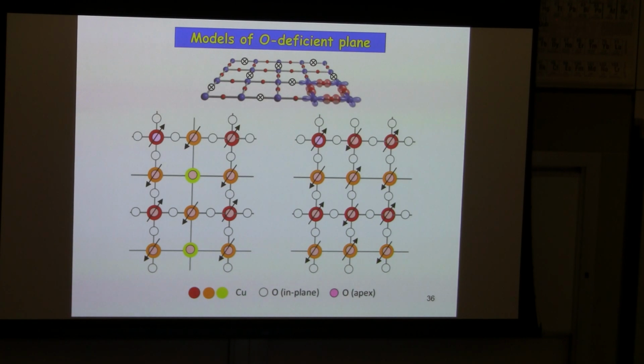Particularly important is that now we have an oxygen deficient copper oxygen plane. In many places, such a superexchange coupling is disrupted, then there is basically no contribution from this four cyclic spin term that is negative to the actual superexchange coupling constant. So we expect that in this oxygen deficient oxygen plane, we expect larger magnetic coupling, but in many models, that larger J might be favorable for higher TC. This is one thing why the oxygen deficient oxygen plane is so important for higher TC.